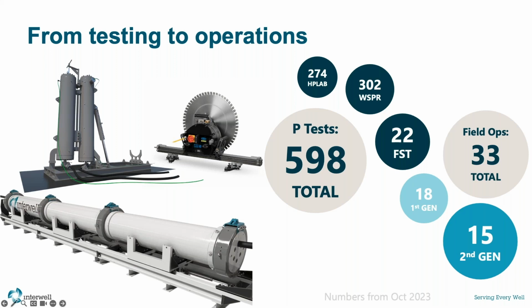Since the beginning of our technology back in 2012, in 2016 we started initial trial field deployments. We did 18 with the first generation tool. And since 2020, 2021, if you will, kind of mixing in COVID, we've done 15 with our second generation tool. So the learnings from the first generation tool, thanks to COVID in part, we were able to go back into R&D and fine tune and modify that process and that product to get to our second generation tool, which is what we're offering today. Generation 1 only created 2 phases of the barrier, whereas generation 2 creates 3. The third element is the actual bismuth alloy that we create from our reaction.